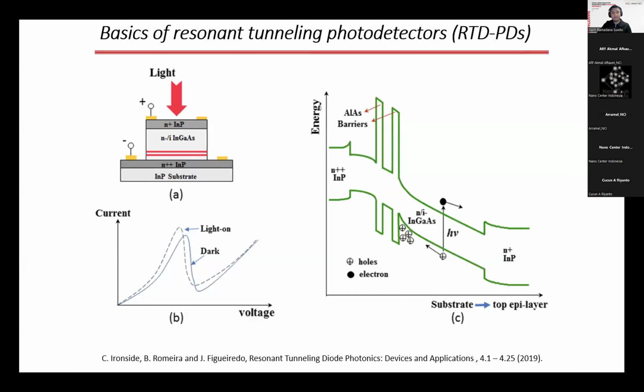So as a result, a redshift is expected to occur on the IV characteristic. When the light is on, the peak gets shifted to the left. Hence, there is a voltage range, for instance in this range in here, in which you could have the largest photocurrent. Basically, the difference between light and dark currents is high in this region, for example.